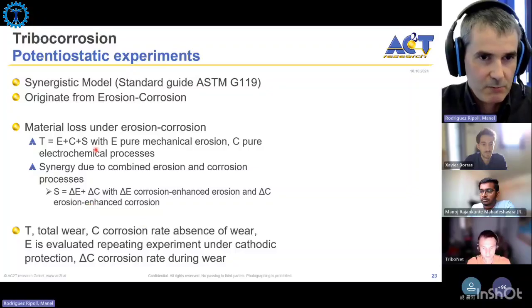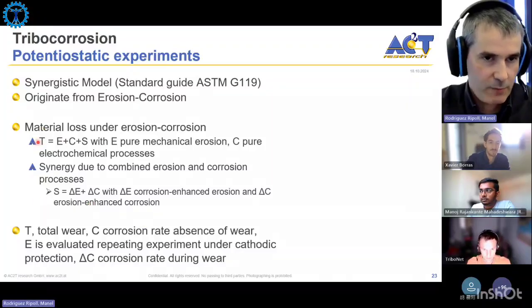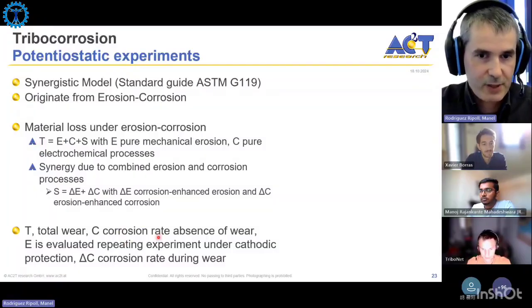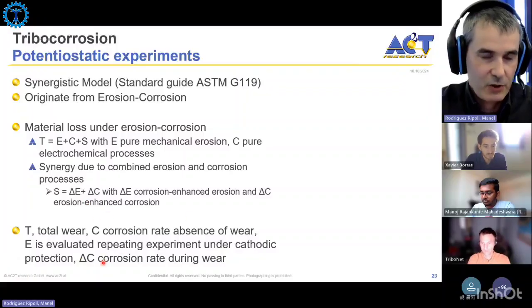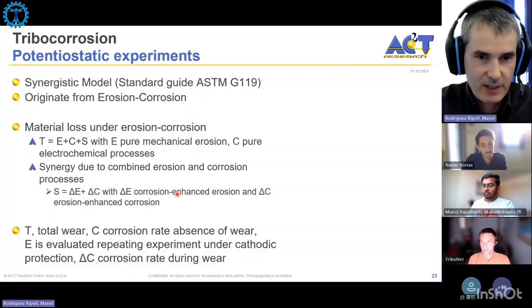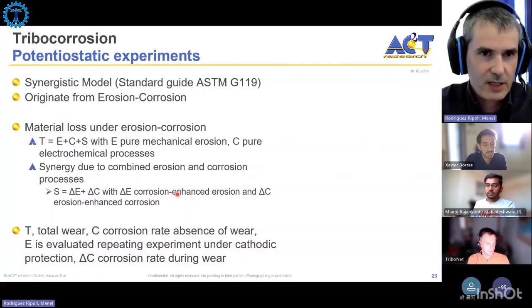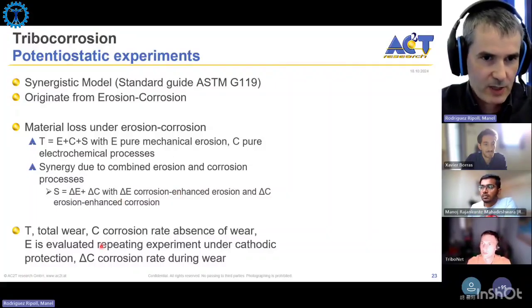Then you can measure, for example, here the total wear is the one that you measure on the profilometry. The corrosion rate in the absence of wear, you can get from polarization curves without rubbing. This pure mechanical wear is the wear that you could get under cathodic protection, and this synergetic term of wear, so this erosion enhanced corrosion, you can get it from polarization curves during the wear process. So the main critics, with this model still very widely used in literature nowadays, arise from the difficulty to interpret these terms, to have a real physical meaning for these terms, and also the challenges to get these quantities experimentally.